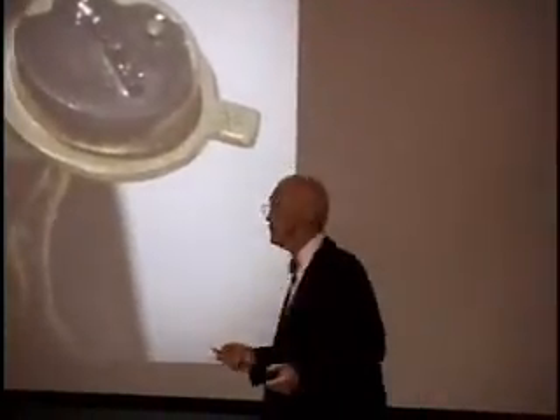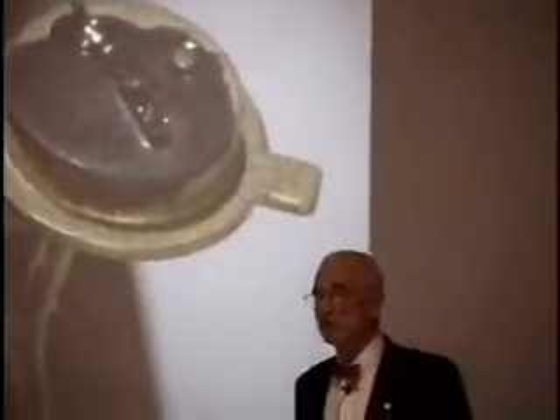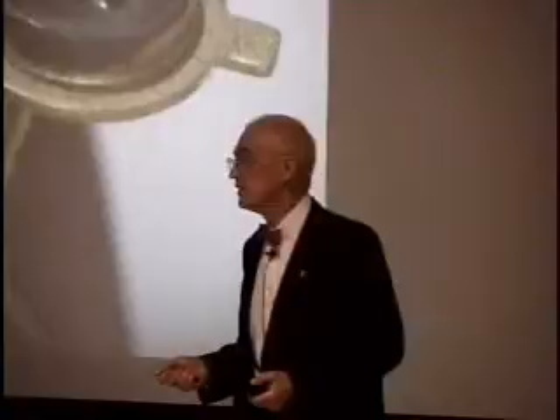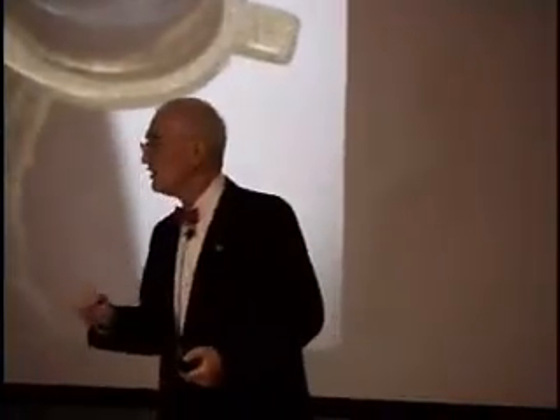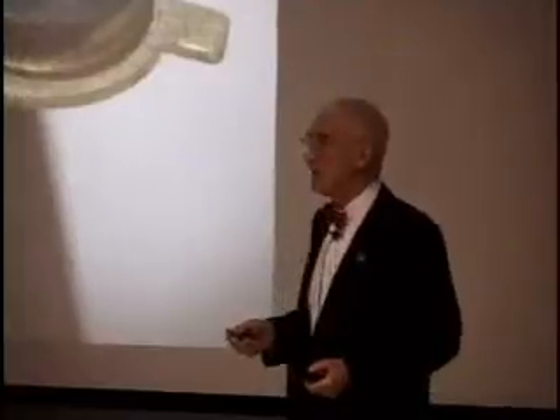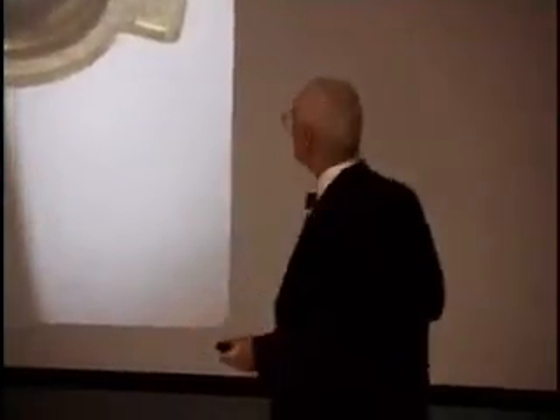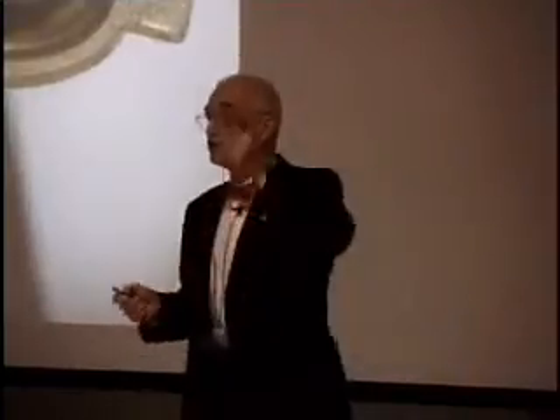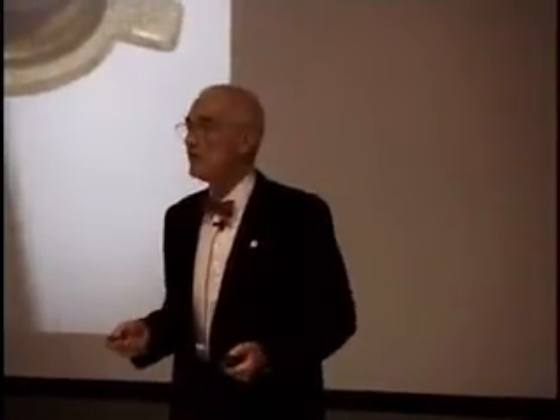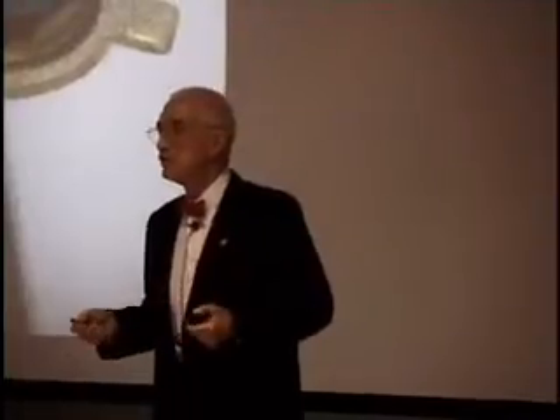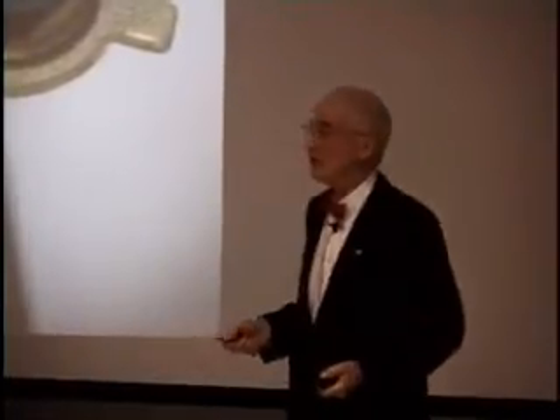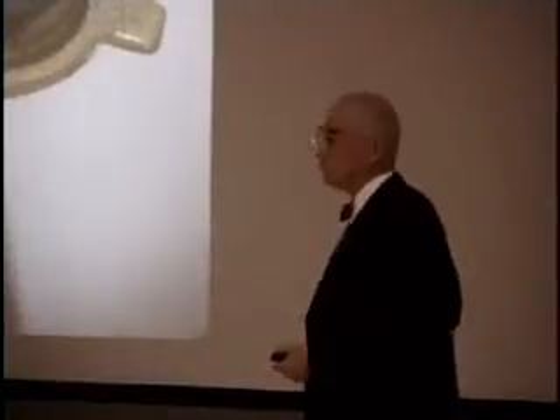We knew how to do it, and we grew gallium arsenide phosphide, diffused a junction in it, made a mesa here, and you're looking at the first alloy device ever. In other words, it's an alloy. It's not germanium, it's not an element, it's not silicon, it's not an element, it's not gallium arsenide, which is a locked binary. It's a ternary. It's an alloy. And maybe it's junk, but if it is good enough to be a laser, it isn't junk. This is the first proof that the 3,5 alloy had device possibilities, and it's important because today you cannot build many lasers and LEDs without alloys. It's not possible. It won't be very good.